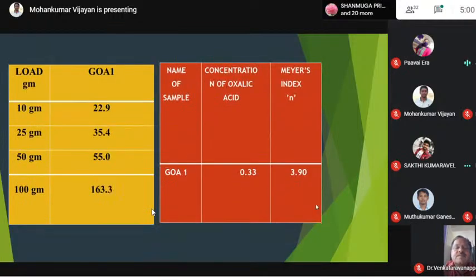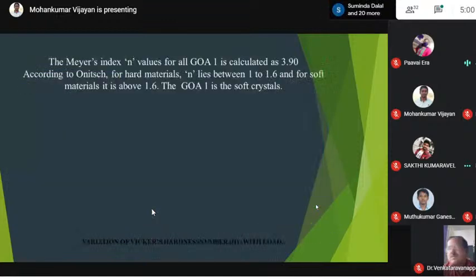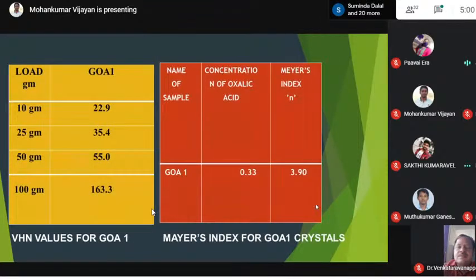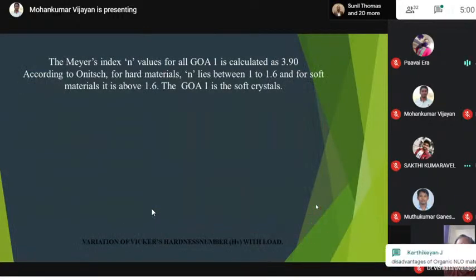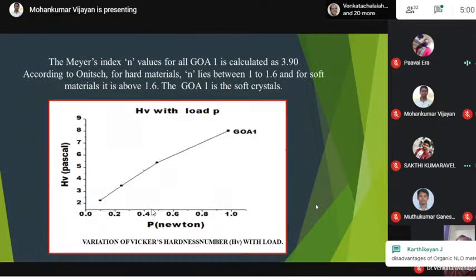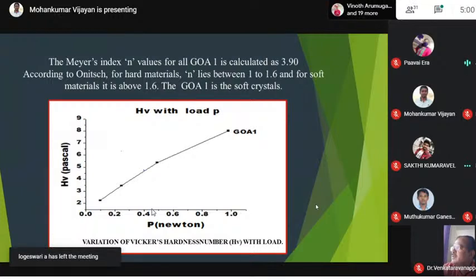This is a table for load and my grown crystal GOA1 and the name of sample. So according to this observation table and this result, we can prove that. The Meyer's index n value for GOA1 is calculated as 3.90. And as you can see in this graph, HV versus P is a straight line graph. So it is very clear that as the load is increasing, the hardness value is also increasing.